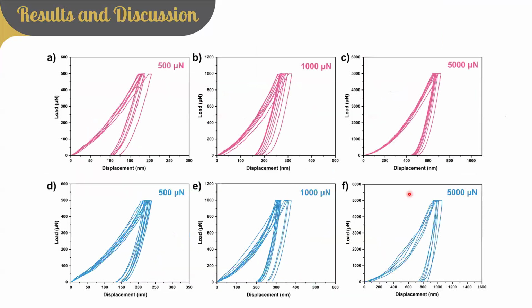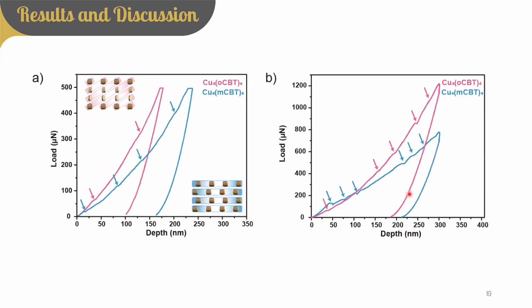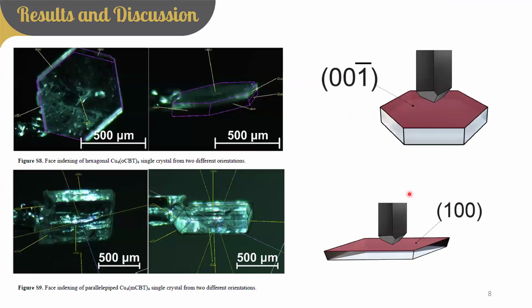Regarding the planes, if you indent on the 0, 0, -1 plane of the copper MCBT cluster crystal, will the indentation behavior be the same? Can we compare like this? No, that's what I told. Crystals are anisotropic, right? So anisotropic crystals will have different properties along different directions. The strength can change if we indent along different planes, but the relaxation behavior is what matters for the Young's modulus and hardness values.